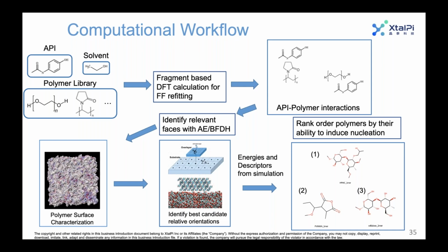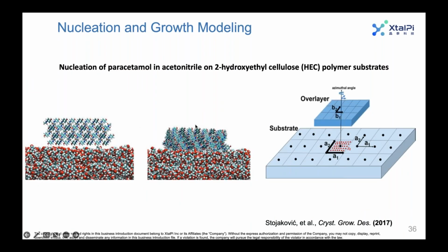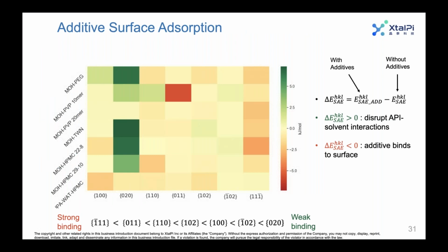That would essentially be, if you're determined to change the morphology from the crystallization, I think polymer additives or surfactant additives would be your best chance. But there would be no guarantee, right? We saw, let me go back just a slide or two. We saw that the polymers change the growth rate of all the faces of metformin HCl, right? But for fast growing faces, it just doesn't change it enough that it can stop those faces from essentially growing their way out of the crystal. It's the slow growing faces that are changed the most by small changes to those small interactions.